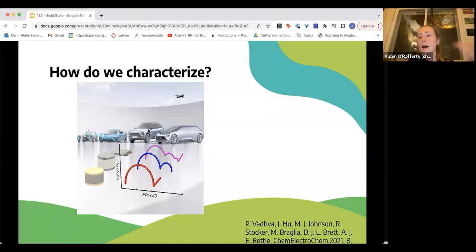The way we characterize batteries generally when we're looking at things like conductivity and resistance is people often use a technique that honestly is quite confusing. There's imaginary parts, but it's called electrochemical impedance spectroscopy. And some people will do this in operando too. So as a battery is running, they'll take this EIS measurement. And you can see, if we're looking at that little red dotted line where the semicircle ends on the x-axis as you go around, that is an important measure of the impedance of the battery. And as the battery degrades over time, you'll see that circle get wider and farther, which is an indication that the battery is degrading.